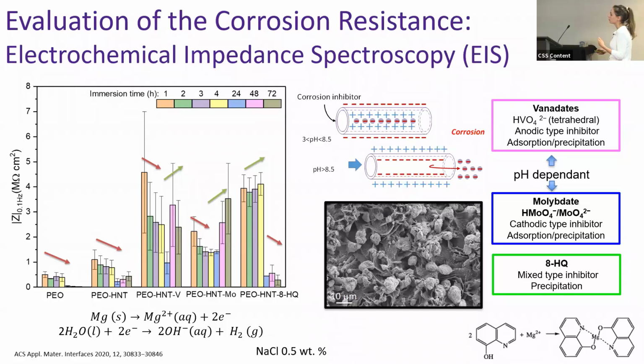after 24 hours. The next set of columns correspond to the coatings containing inhibitors. For all of them, and for all the immersion times, the corrosion resistance was considerably higher. In the case of the two inorganic inhibitors, vanadate and molybdate, we can see that they follow the same trend. First, the corrosion resistance decreases after 4 hours, reaching a minimum at 24 hours, and then the corrosion resistance increases considerably. So probably it wasn't until 24 hours, well, as I mentioned before, these two inorganic corrosion inhibitors will be released from the nanotubes when there is an increase of pH. So probably it wasn't until 24 hours that the change in pH was significant enough to trigger the release of the inhibitors from the nanotubes. Once they were released, they act at the anodic and cathodic sites, not only hindering corrosion propagation, but also improving the overall corrosion resistance of the coating.